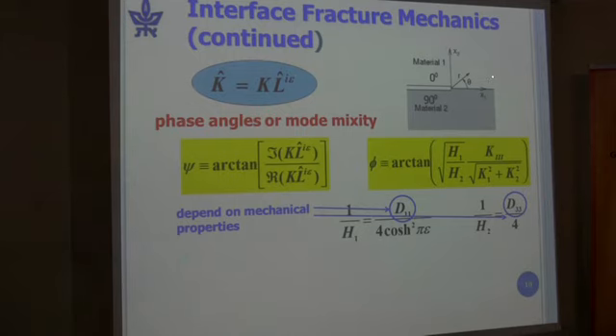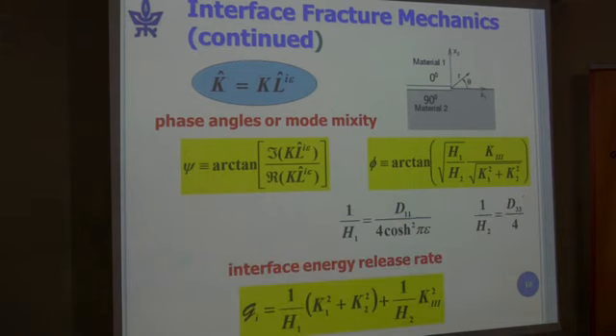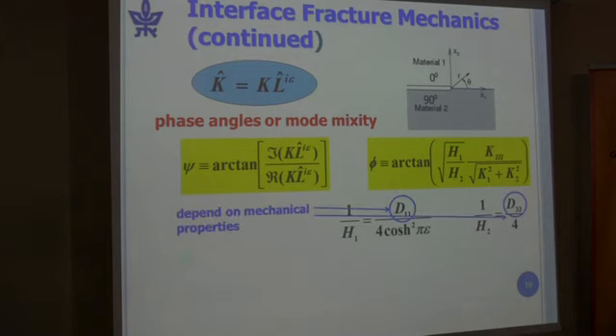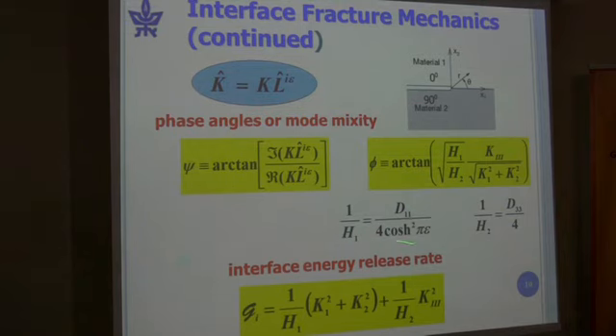are Young's modulus type quantities. For somebody who is familiar with the relation between G, the energy release rate, and K, you have 1 over E or 1 over E bar generally in homogeneous materials. So here we have this H1 and H2, and both epsilon and these D quantities depend on mechanical properties. So you can think of H1 as being Young's modulus, if it makes it simpler. And then we have an expression for the interface energy release rate. And so it's very similar to homogeneous materials.